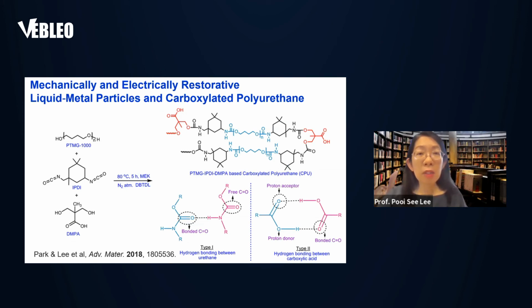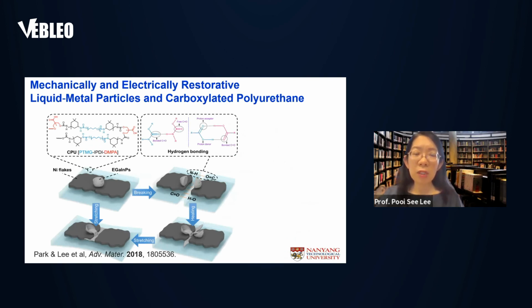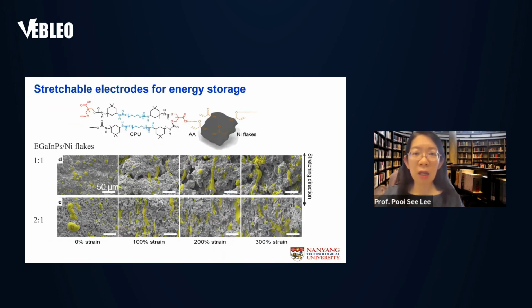So having the elastomeric material is useful, but we would like to have chemical interaction between the elastomer and the liquid metal particle or the metallic flakes that we have introduced. So in this case, we thought of modifying the urethane material with a functional group of carboxylated because it provides then abundant carboxyl groups for the incoming fillers like metallic conductors. So with this approach, we introduce the nickel flakes, which are more stable for electrochemical applications. And indeed, it works well where the carboxylated PUA elastomer leads to highly stretchable and healable electrochemical active conductors.